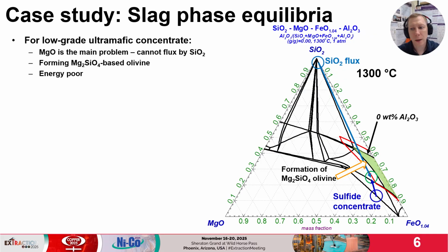Here we have simplified slag chemistry of the smelting process. The diagram is at 1300 degrees and relatively reducing conditions corresponding to low grade matte. In nickel smelting, we need to flux iron with silica, but compared to copper smelting, high content of MgO in concentrates requires increased temperature. The region of fully liquid slag is highlighted. It is limited by the formation of spinel from below, the formation of Mg2SiO4 olivine from the left, and tridymite from the top.